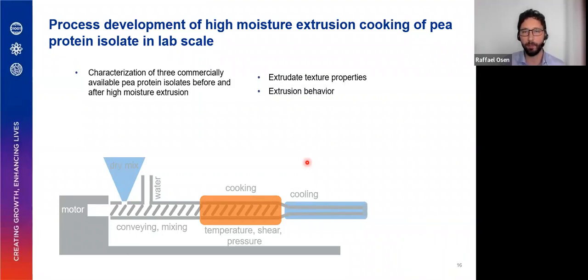So when we started this work, most of the literature was done on soy protein plus wheat gluten. So then we used pea as an alternative raw material, and then looked into how we can come up with a high moisture extrusion process to texturize pea protein, having a simple model recipe, and for that we use pea protein plus water. And then how can we, by characterizing the protein, find out some explanations of why the proteins might have different extrusion behavior or different extrusion texture properties.